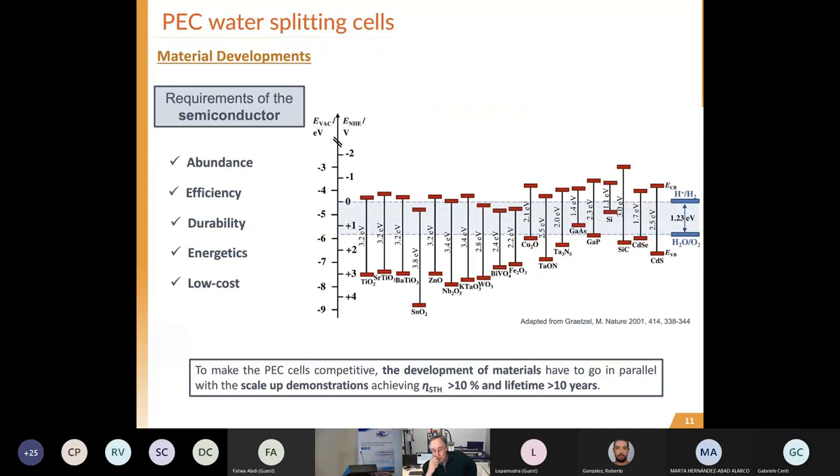When you use a photoelectrochemical cell, there are several problems. Up to now, only hematite has proved to be stable - this is the first challenge. The second challenge is that the photoelectrochemical material must match the energy levels for the electrolysis of water, which greatly limits the number of viable photoelectrodes. It has to have a band gap that is not too large - otherwise you won't absorb much solar energy - but it cannot be too small either, otherwise you don't have enough photovoltage. It should be stable, and many other things. Actually, there is no ideal viable photoelectrode. We have very good photoelectrodes, but they are mostly unstable.